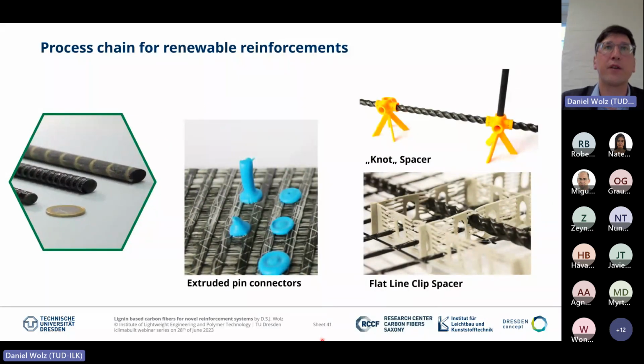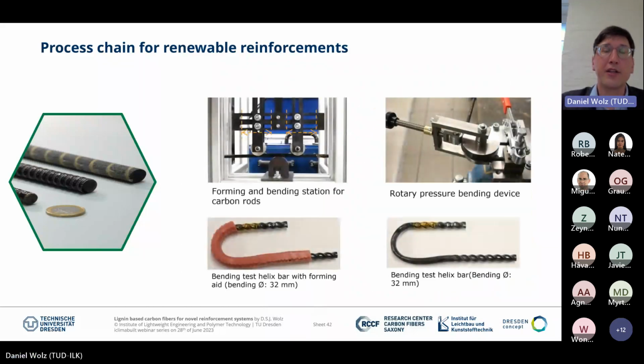Still, at the end, we have to bring the reinforcement rods into the carbon concrete. Therefore, different spacers, extruded pin connectors, and flatline spacers have been developed to maintain the application processes at the construction locations, the same as for reinforcement rods. Additionally, we have to build anchors, which also have to be manufactured within the systems we have. Therefore, a forming and bending station for carbon rods has been developed, with forming aids or rotary pressure bending devices, producing the anchors we need to combine the different reinforcements for the rods.